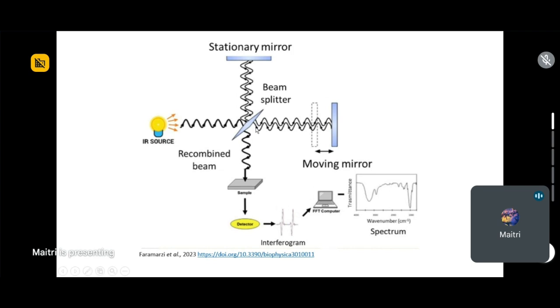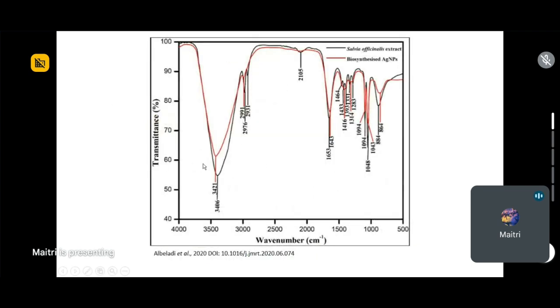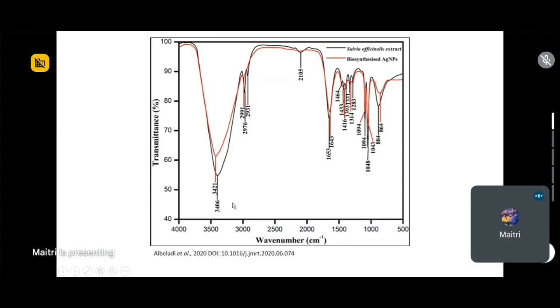Now, this is just the instrumentation of the FTIR, but this is the actual graph. So, what does this tell? Red is for the AgNPs and black is for the extract. So, see, this peak got reduced, means this peak was used for the reduction of AgNPs. Whereas here you can see there is some slight shifting in the peaks. So these peaks were used for capping. Like even here you can see some very slight shift between the peaks. So these peaks have been used. All these peaks correspond to certain functional groups. So we can say that these functional groups have helped in the capping of the AgNPs, whereas these peaks, these functional groups have helped in the reduction of the silver to AgNPs.